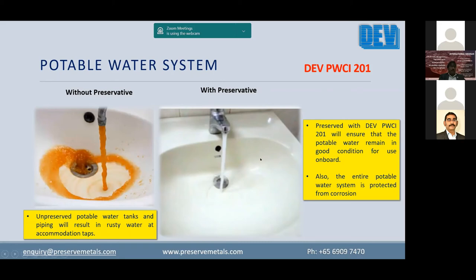This additive meets the FDA requirement for drinking water applications. As a result, this is again a very low-cost and very effective solution. The initial dose will be 1000 ppm, but for subsequent use it reduces to 75 ppm. At that level, we are able to assure that the water is drinkable. At the same time, internally there is no corrosion and no claim from the client for problems on board the vessels that have been supplied.